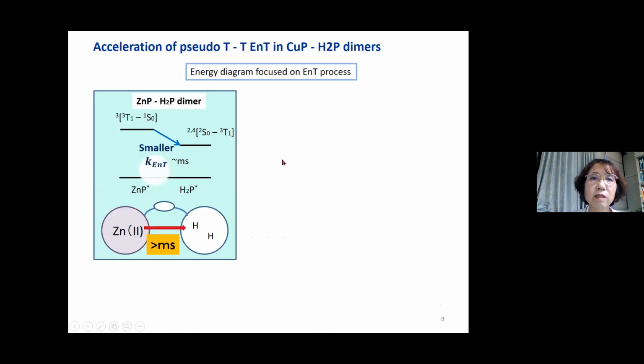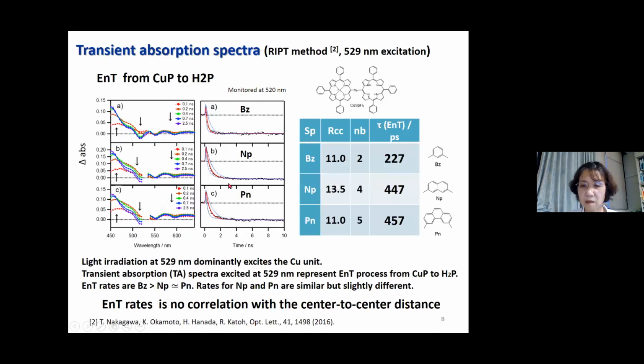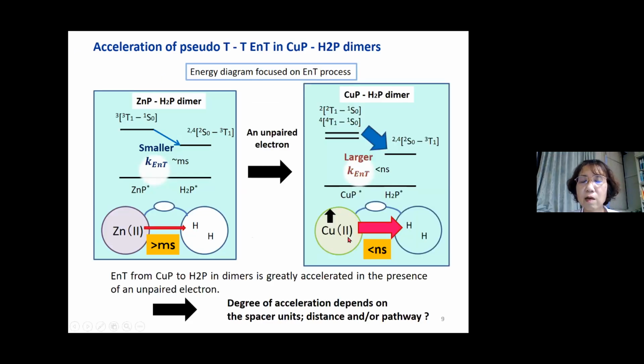So just let me explain what we have observed by the transient absorption. In the case of a diamagnetic zinc porphyrin free base porphyrin dimer, energy transfer from the zinc porphyrin triplet to the free base triplet is very, very slow, and the energy transfer rate is approximately milliseconds or longer. However, if we have one unpaired electron in the donor, the energy transfer rate is quite accelerated. It is observed in less than a nanosecond, and this rate depends on the spacer units.